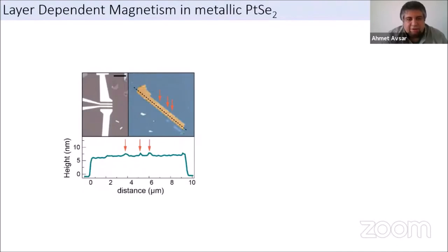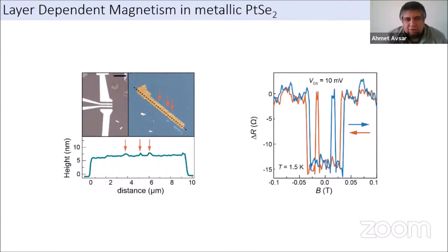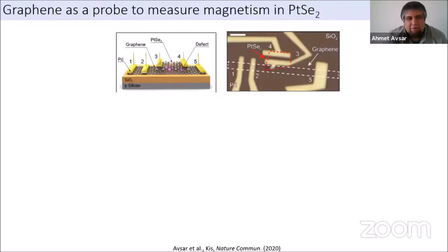And indeed, we also had a chance to check another device. So this is a platinum diselenide. I think it's not very obvious here, but at the position where we have these arrows, we have indeed one step height materials. Okay, so this AFM scan, you could already see. And we measured also the magnetic response in this device. And what we could see is indeed a combination of both ferromagnetic and antiferromagnetic types of signal that we see in the same device. We do believe that some contribution is coming from these layers, which have an additional layer, and the other ones have just a ferromagnetic response.